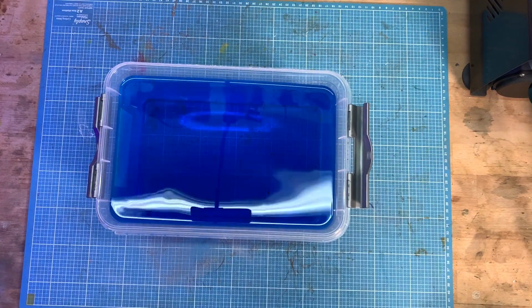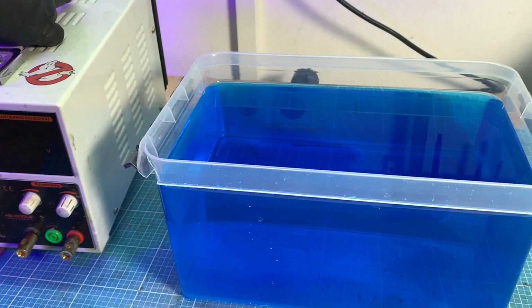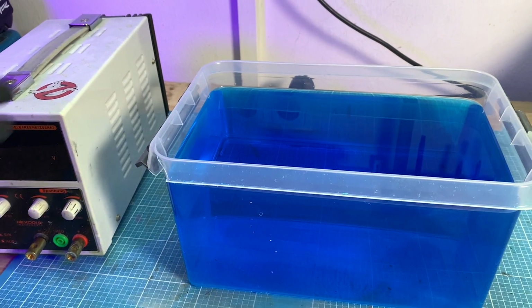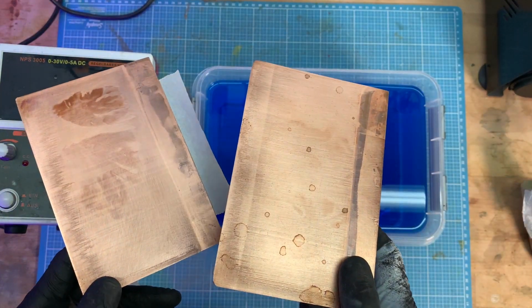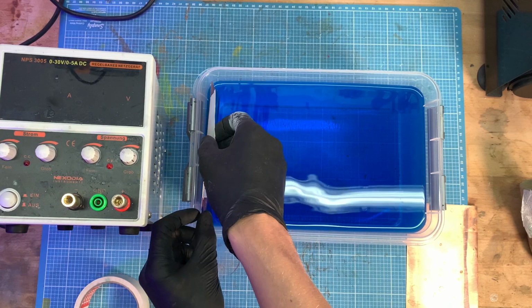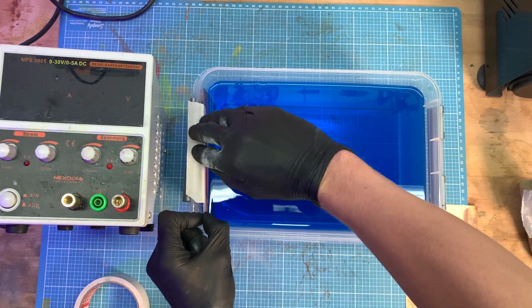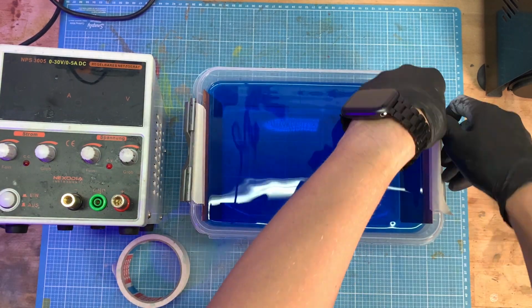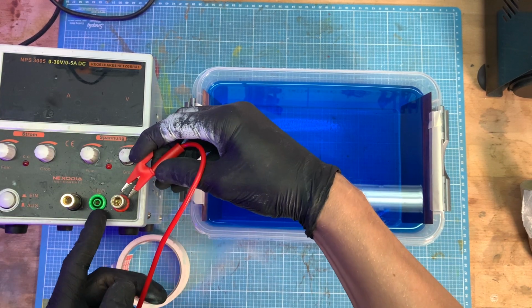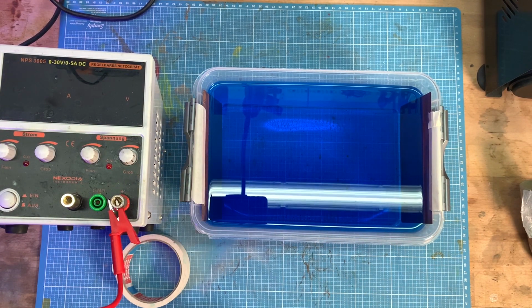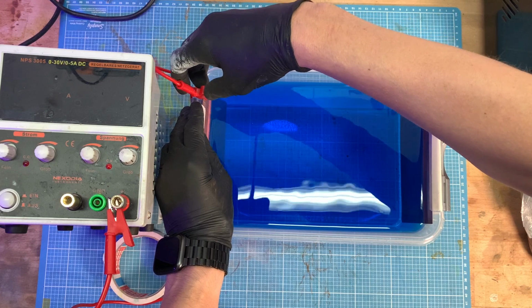And this is where the fun really begins. We will now bath electroplate the object. For this, I use a copper electrolyte. You also need a power supply. These copper sheets are the anodes. They are fixed at one and the other end in the bath. Also pay attention to the wiring. I now connect the anodes to the positive pole of the power supply.